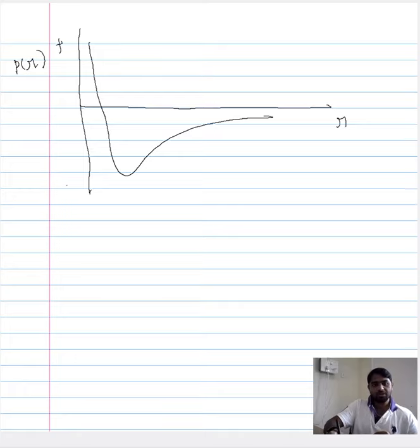So we have a positive quadrant and we have a negative quadrant. This is the interaction between two atoms when you vary its position. And when you plot the change in the interaction potential with respect to its position, it is not symmetric in nature. That means the atoms are allowed to move a bit farther away from each other compared to their movement close to each other, and that leads to the thermal expansion, and that was our understanding in the previous lecture.